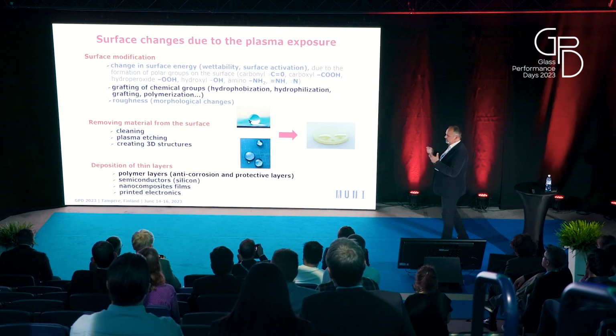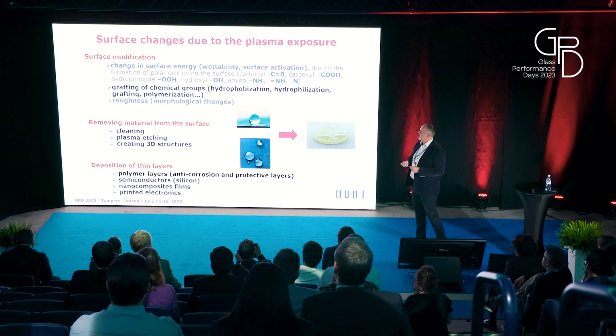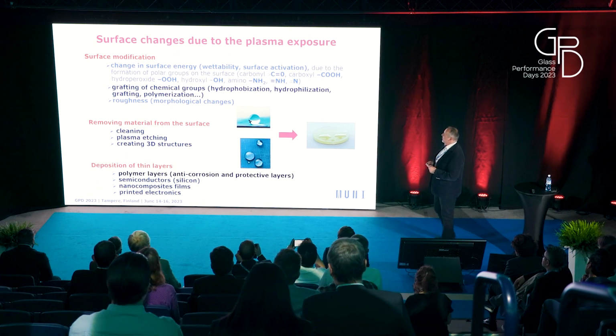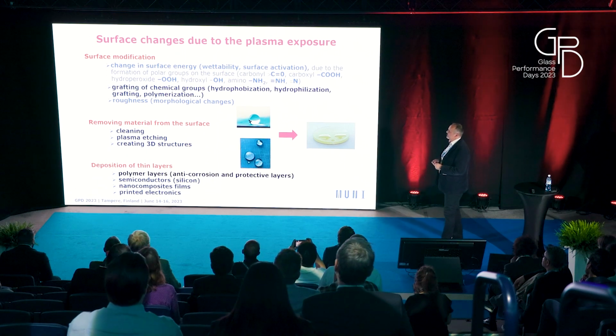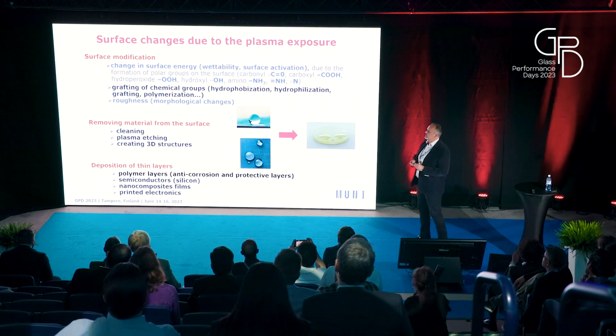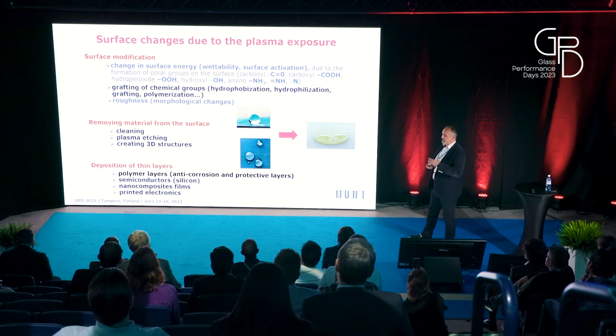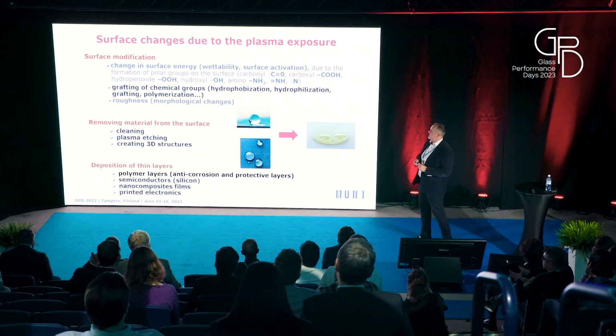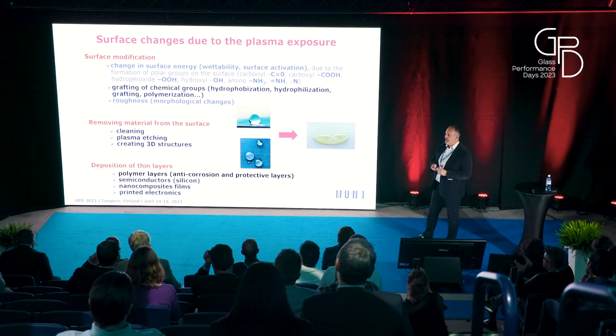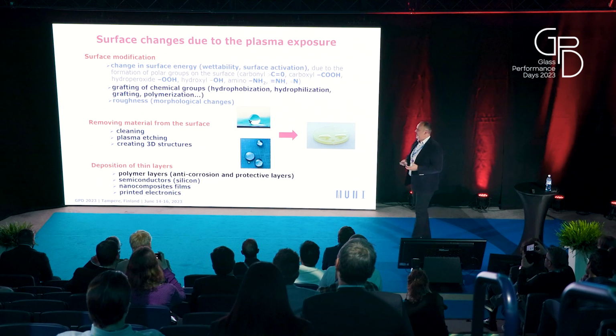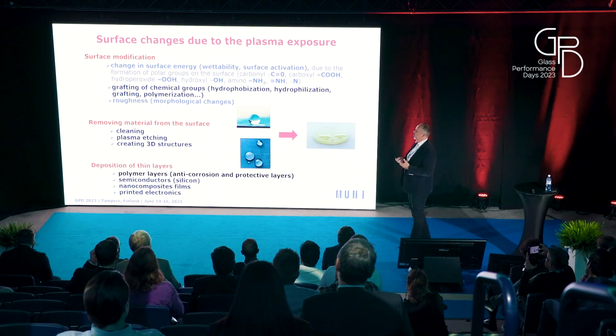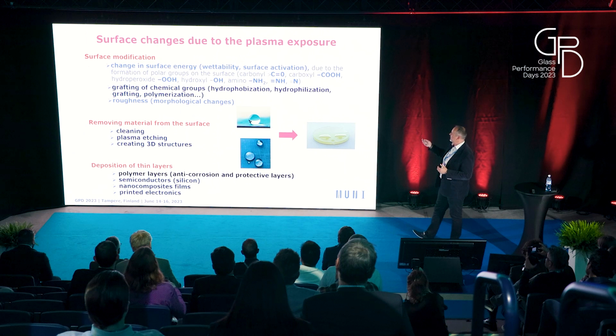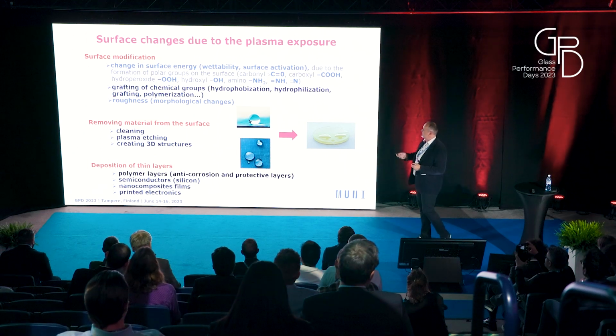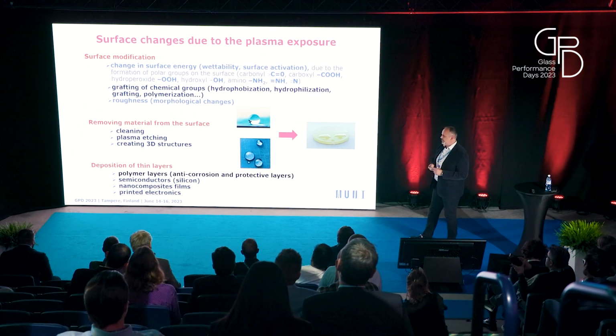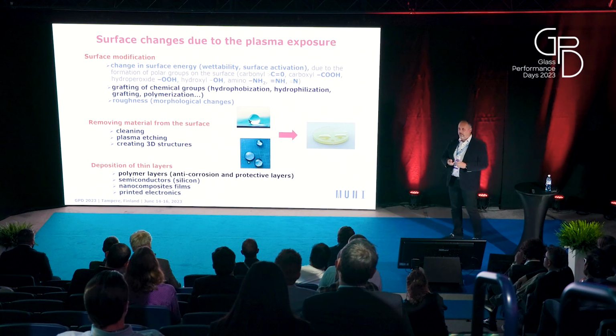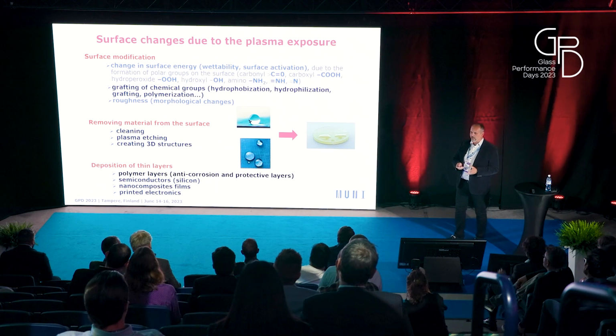Plasma can be used for different purposes, but if we are talking about surface modification, what plasma can influence is the change in surface energy. We can change wettability, we can activate the surface or make functionalization. If we generate plasma in ambient air, we predominantly form polar groups on the surface like carbonyl, carboxyl, hydroperoxide, hydroxyl, or amino. But using the plasma, we can also change the roughness, and we can talk about the morphological changes.